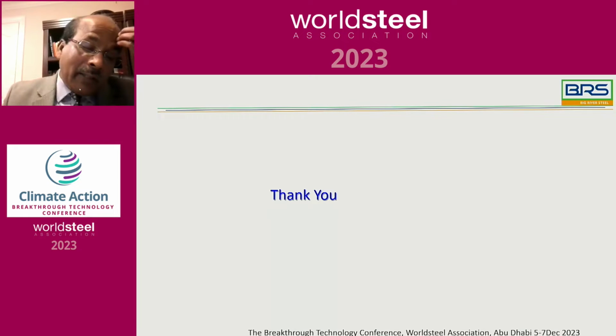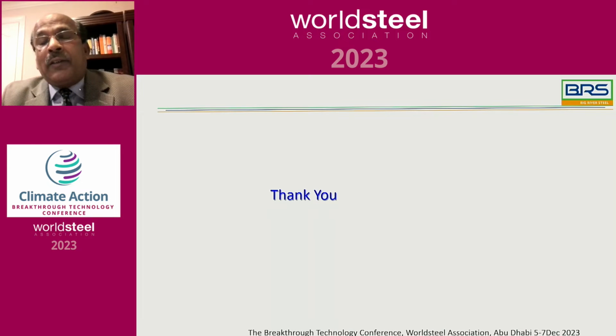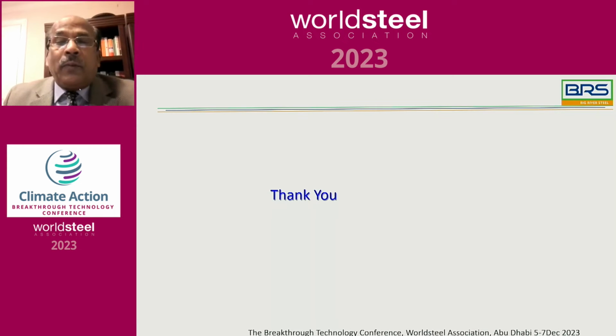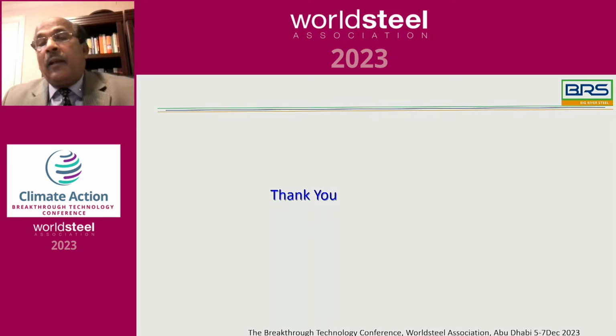Thank you, that's a great question. The processing of this steel is very straightforward. In the hot rolling condition, you just have to control the finishing temperature and the coiling temperature. The finishing temperature has to be in the range of about 1550 to 1670 Fahrenheit, so that you don't grow the titanium carbide precipitates during the finishing deformation stage. You have to cool down very fast from this finishing temperature to the coiling temperature stage, so that most of the titanium remains in solution, and the precipitation occurs during the coiling stage in the hot band coil and remains very fine, so you don't overgrow the precipitates.